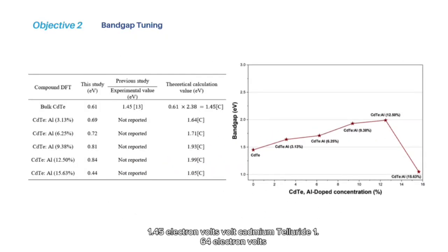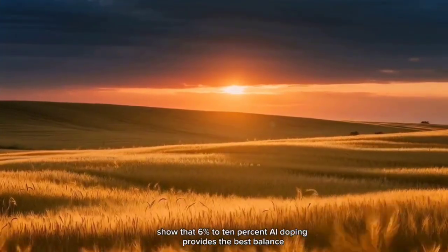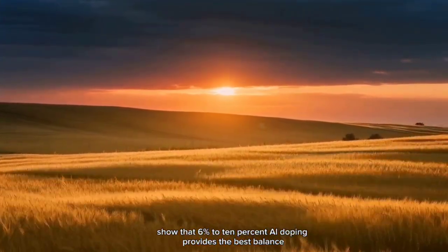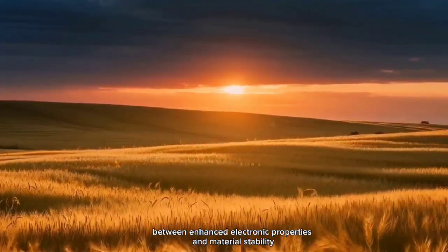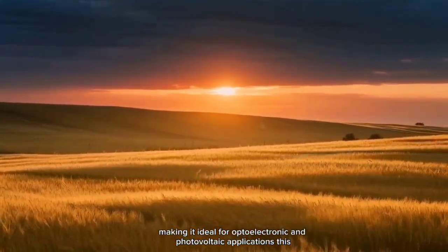Band gap values: 1.45 electron volts, bulk cadmium telluride; 1.64 electron volts, 3.13% Al; 1.71 electron volts, 6.25% Al; 1.93 electron volts, 9.38% Al; 1.99 electron volts, 12.50% Al. Beyond 12.50%, the band gap drops to 1.05 electron volts, suggesting structural defects and reduced electrical properties. Our results show that 6% to 10% Al doping provides the best balance between enhanced electronic properties and material stability, making it ideal for optoelectronic and photovoltaic applications.